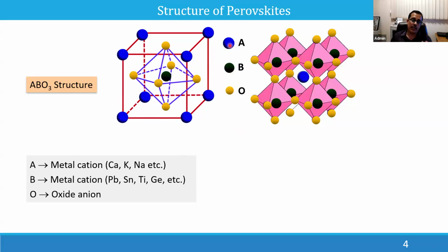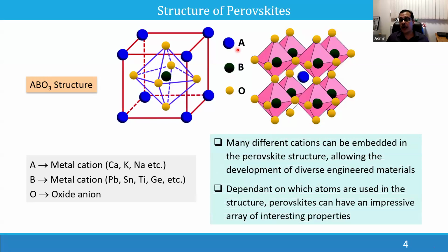Initially, the B cation is situated in the middle of the octahedral structure, and the oxide anions form the octahedral structure. Several of these octahedra are combined together to form a 3D structure. When the 3D structure is formed, there will be interstitial voids, and these voids are filled with A cations. You can embed different cations in the A site as well as in the B site, and depending upon which cation you are using, you will get an impressive array of properties.